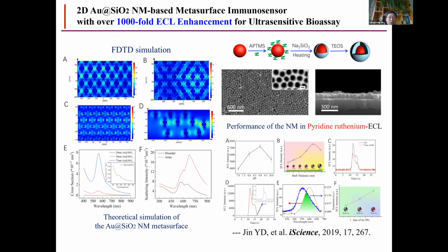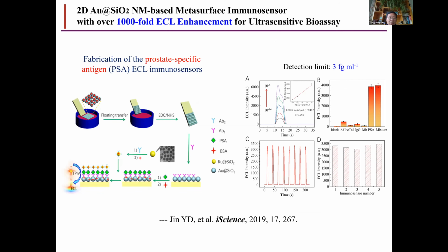Very recently, our interest in nanostructures moved to two-dimensional gold nanoparticle-based nanomembrane. Here shows a nanomembrane prepared from gold silica core nanoparticles, due to well-defined core structure and arrangement. The electromagnetic field has been intensified in the film. Also, the cross-section and scattering intensity have significantly been enhanced, so it shows over 1,000-fold ECL enhancement in the pyridine ruthenium ECL system. We further built a prostate-specific antigen ECL immunosensor. Such a sensor showed good selectivity, reproducibility, and a very low detection limit for PSA detection.